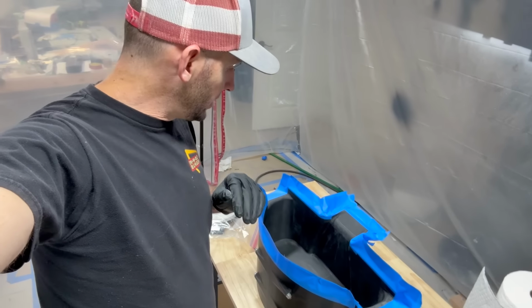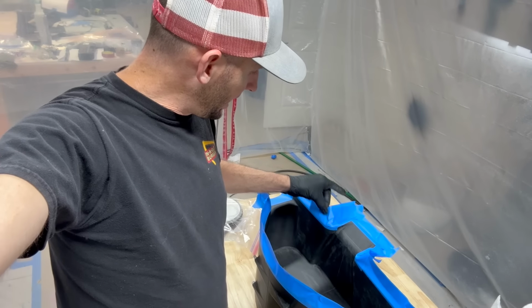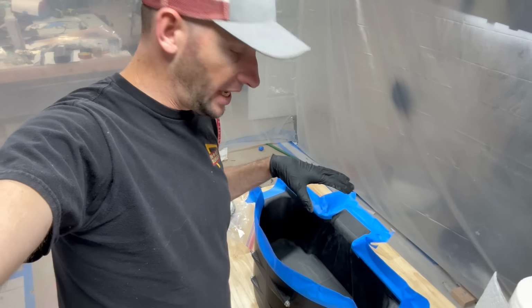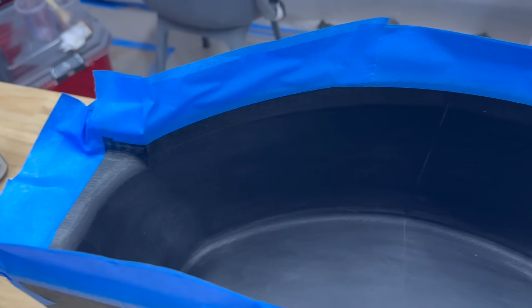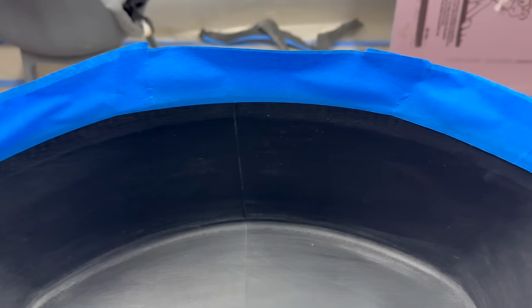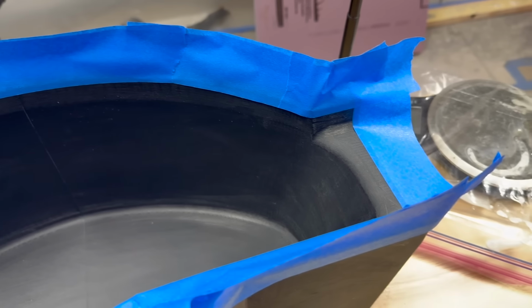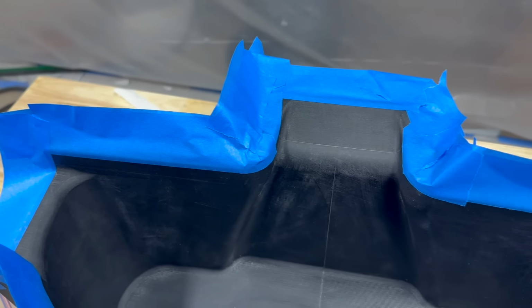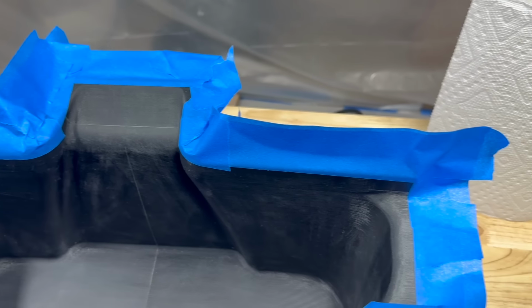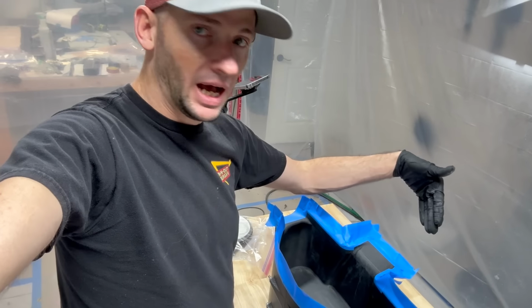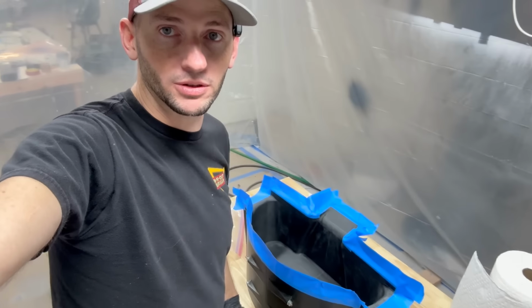All right, the mold is mostly prepped. You can see I added kind of a makeshift flange out of blue masking tape. This will keep any of the material, if it does come out of the mold and starts to lay over the edges, from mechanically locking itself in the mold, and it'll give me something to get behind the part to help release it once it's finished.